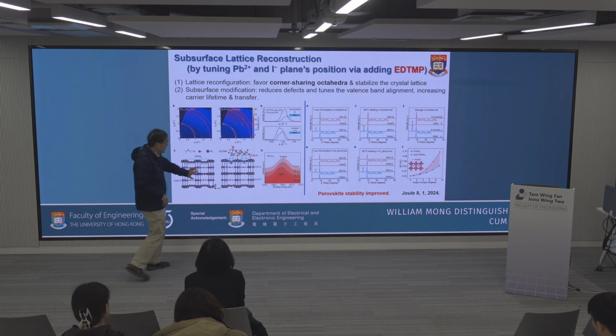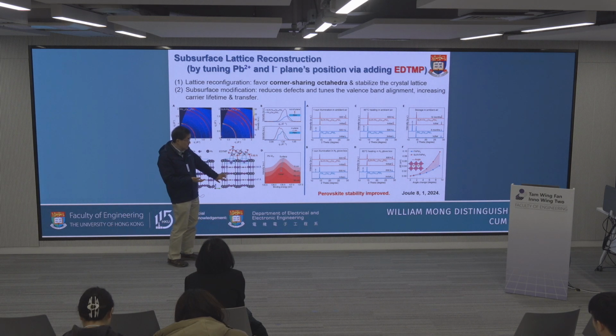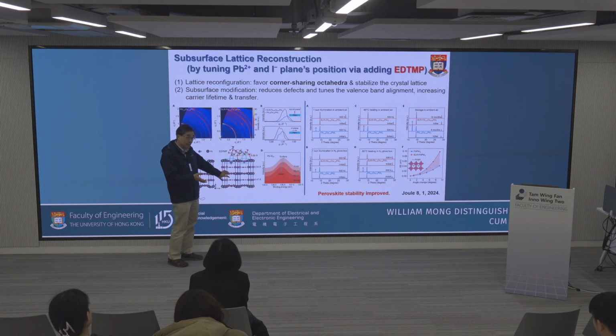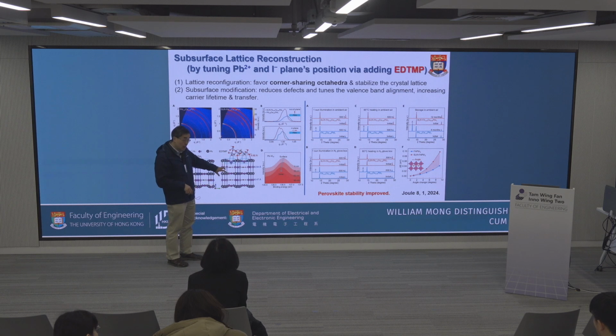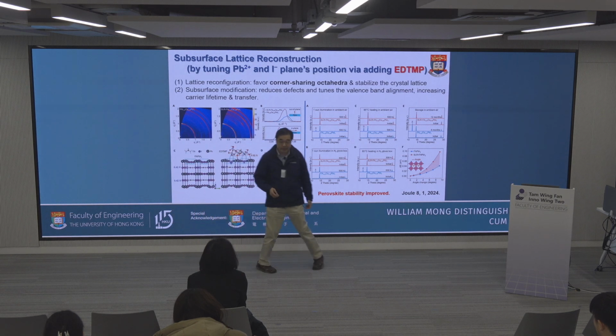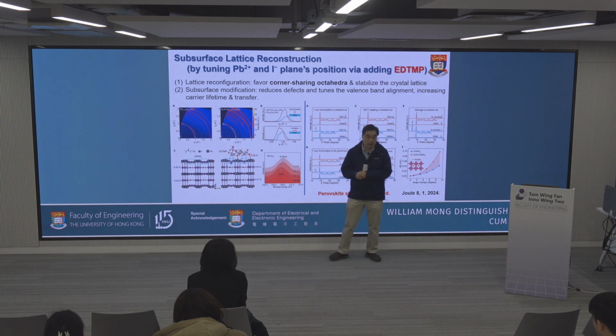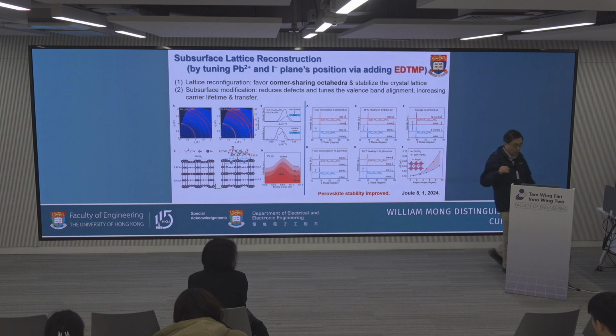We all know the bulk inside has good quality corner share crystalline, but the surface, because it's no longer the last layer, the crystal is not that perfect. What we do here is allow the small molecule to maintain the corner share perovskite up to the top regions.